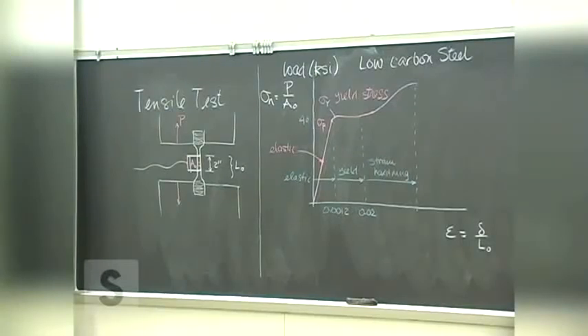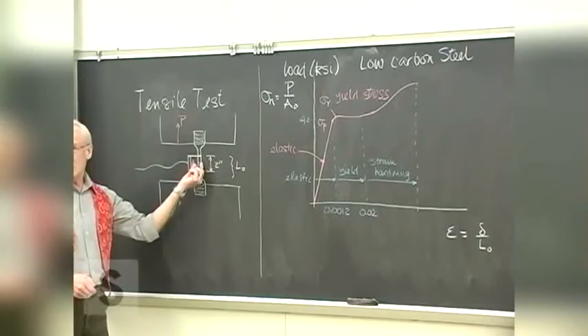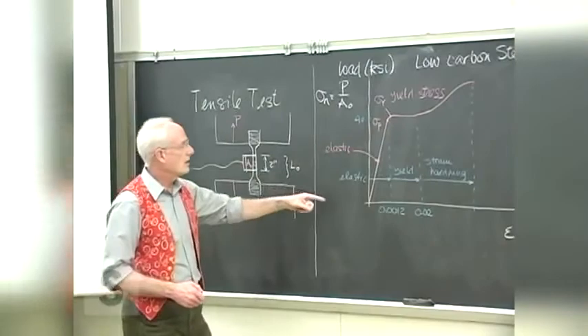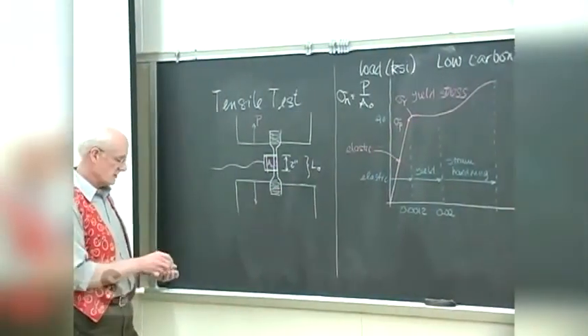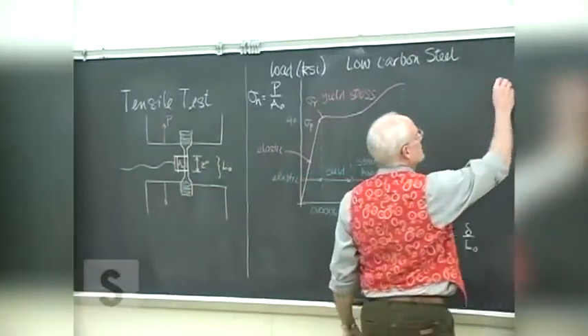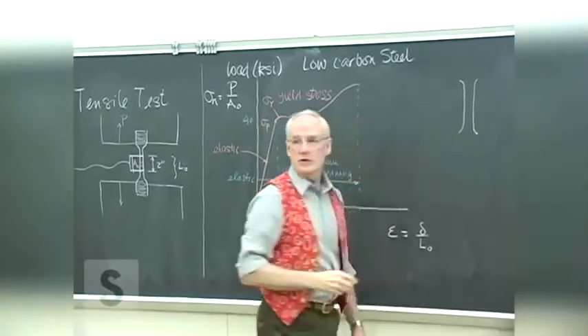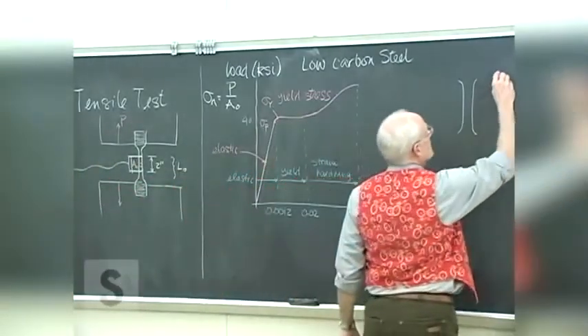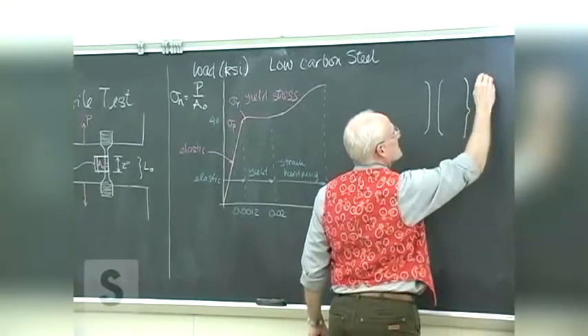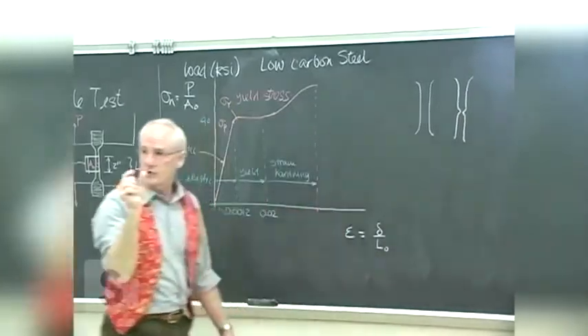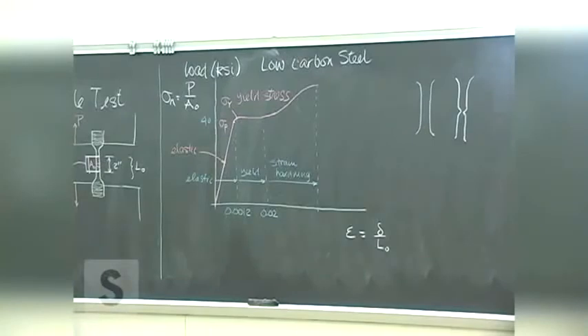Then after this, and you've seen this if you've looked at the video, the material has not had an appreciable change in the cross-sectional area. So all of this region is pretty much as divided by the cross-sectional area in calculating the stress. But then from here on, the material starts to go from this nice, generally cylindrical shape that it has in here. It starts to do what is called necking, where at a region somewhere in the middle, it actually starts to decrease substantially in its cross-sectional area as the load increases. And you can see that if you look at the videos carefully enough. I think in one of the videos, they even stop it right there and say, you can see that the material is necking now, and they even put an exclamation mark after it because it's a very exciting time.